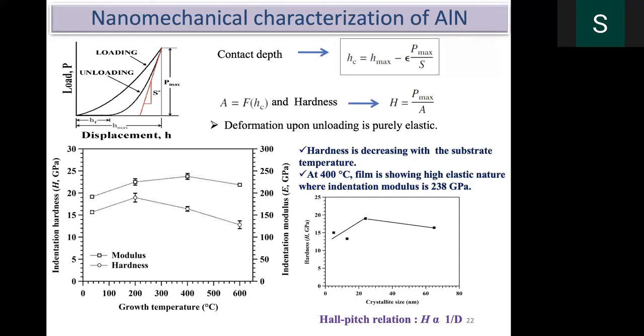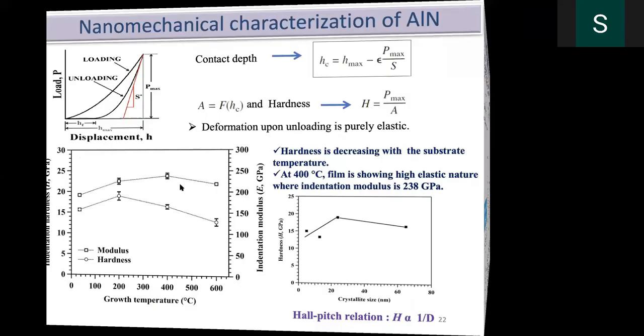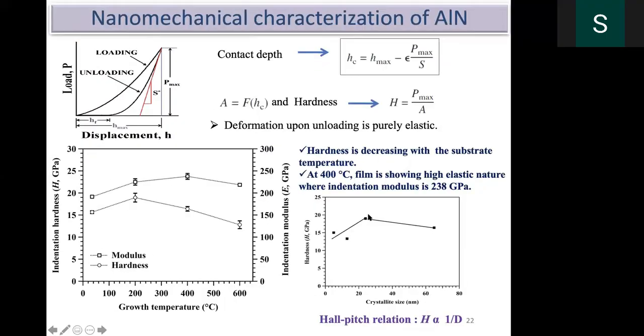At a particular point, the transition will occur. So, maybe somewhere here, the hardness will reduce. That means if you go below and below, dislocations cannot be discussed in an amorphous material because there is no definite grain boundary, and below that the material shows less hardness compared to crystalline or pure grain materials.